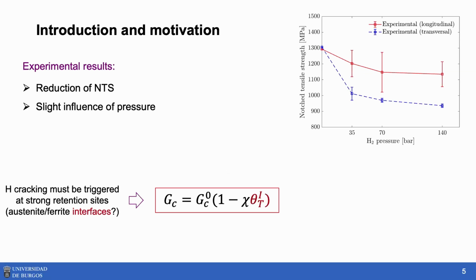In our case, we are not using a general coverage. We are using the occupancy of a kind of trap. Since we see that after a high pressure we don't observe a stronger embrittlement, we are assuming that embrittlement must be triggered at the very strong retention sites. From literature, we deduce that they should be austenite-ferrite interfaces. Of course, this is also open to new interpretations.